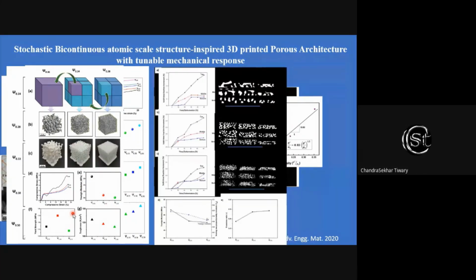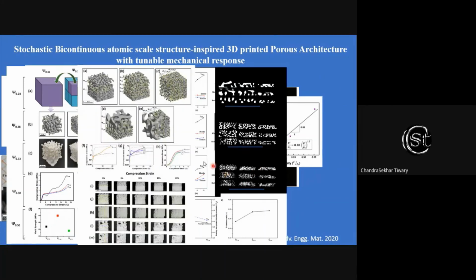Apart from that, these deformations are different in different regions, and you can see if you have a coarser structure, the load transfer is fairly high, whereas if you have a fine or more surface area structure, the load transfer is localized.